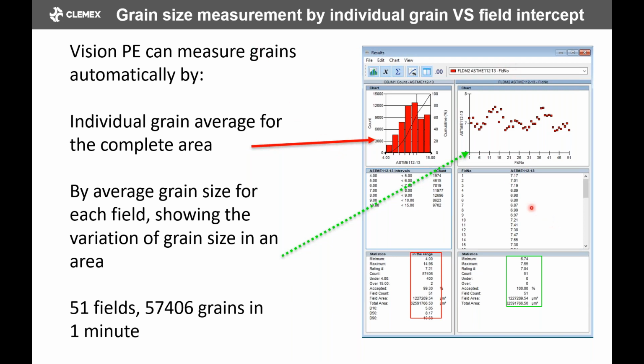For the grain size measurement, that's what we just talked about: the grain variation by object. We end up with some interesting statistics. We measured 57,000 grains in about a minute. So it doesn't take long to measure something interesting or representative.